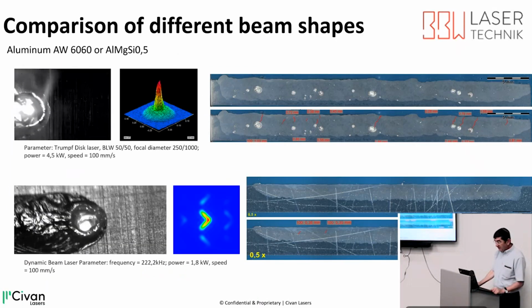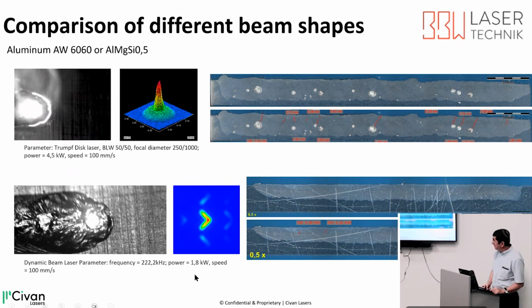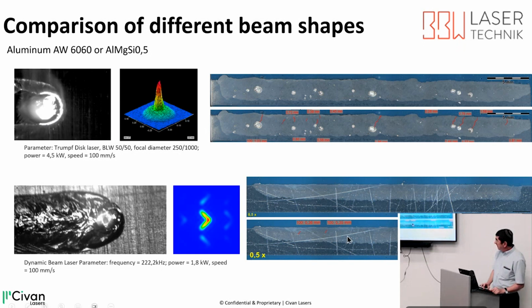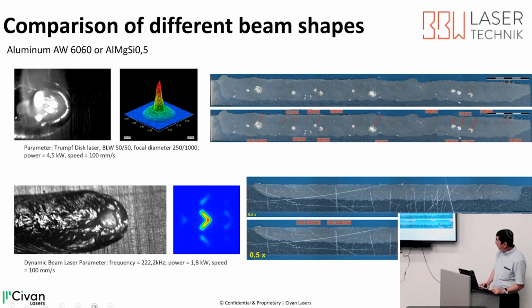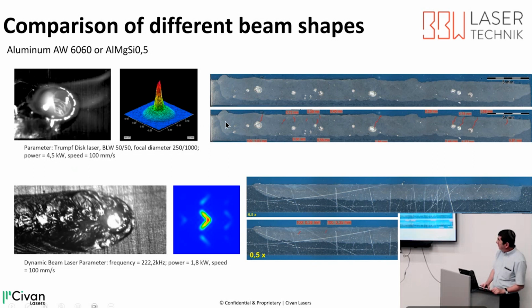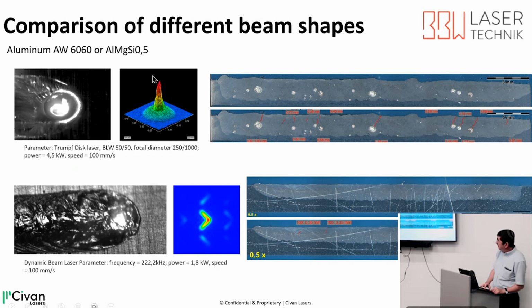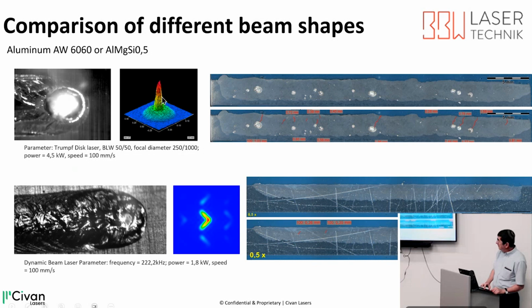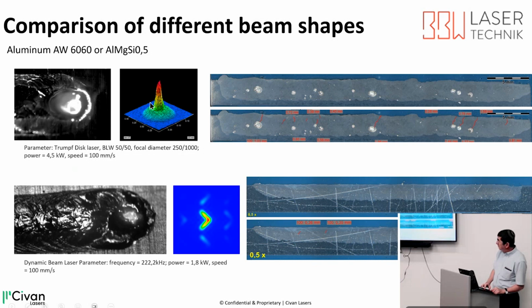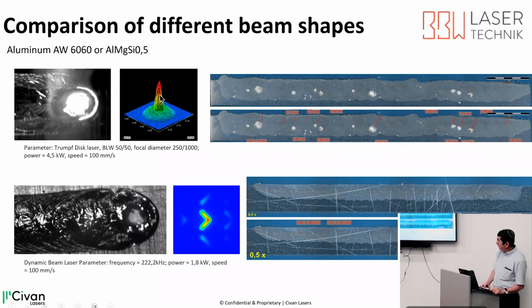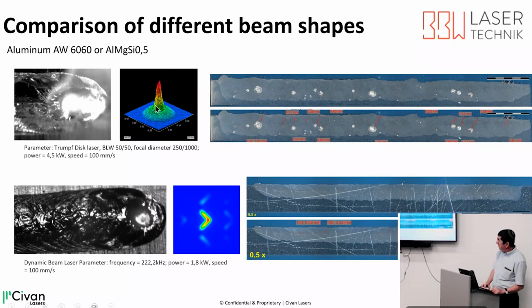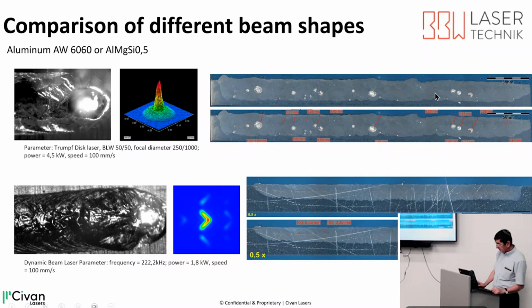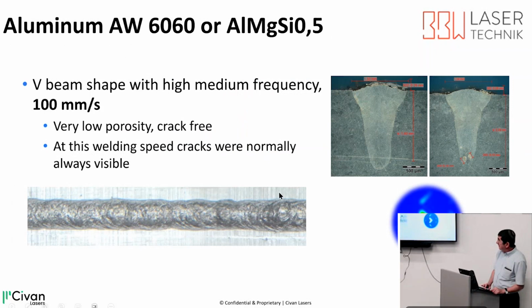So this is BBW, where they designed this beam shape that creates some motion in the melt pool, and you get a perfect weld compared to a standard laser of IPG or TRUMPF, where the most beam shaping you can do is make some kind of a ring with some energy in the middle. This is the best shape that they can reach, but still you have here a lot of porosity, and usually you have cracks, and here you see there's no cracks. So with our beam shape, they're able to do no porosity and no cracks.